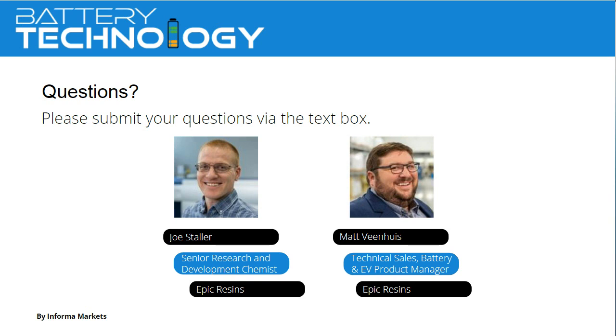What's the range of thermal conductivity that your products have? Matt Veenhuis here. Our products will carry anything from the unfilled systems at around 0.1 watt per meter Kelvin, all the way up to over 3 watt per meter Kelvin. Most of the time we're looking at finding the right product that meets the application. Obviously, when you go higher in thermal conductivity, there are other things that happen, such as an increase in viscosity, but the range is anywhere from 0.1 up to greater than 3 watt per meter Kelvin.